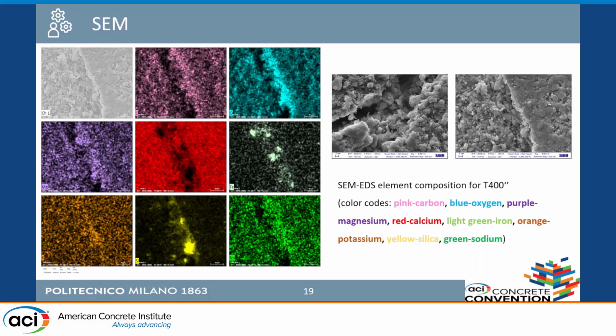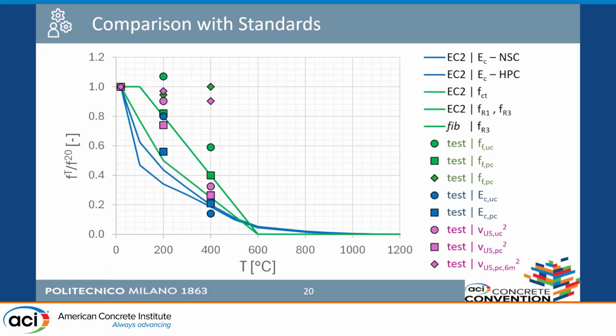And typically what is important is the hydration of CSH and the precipitation of calcium carbonate. So this is the picture that I was really interested to show you. This is the same curve that we discussed in the second slide, I guess. So what we obtained from EC2 and FIB for the hot behavior of the material. The dots represent the results of the experimental test.